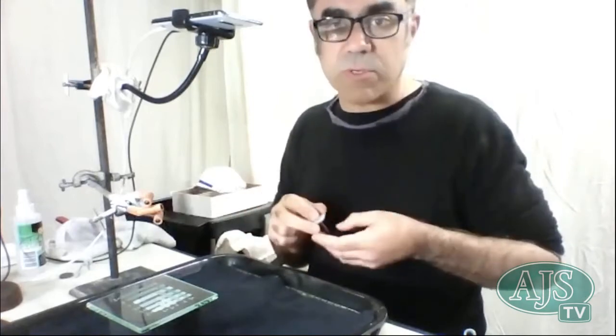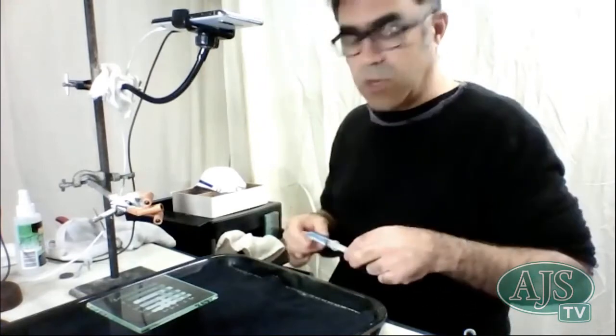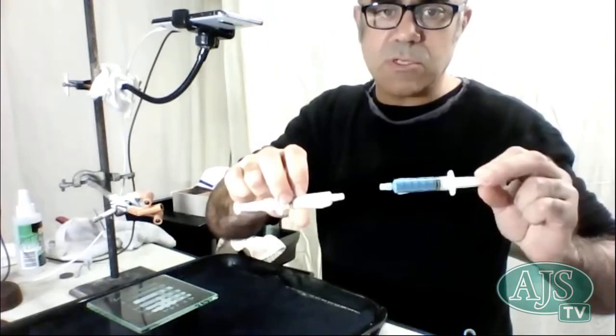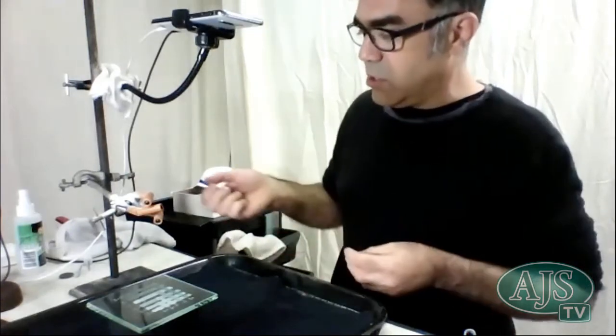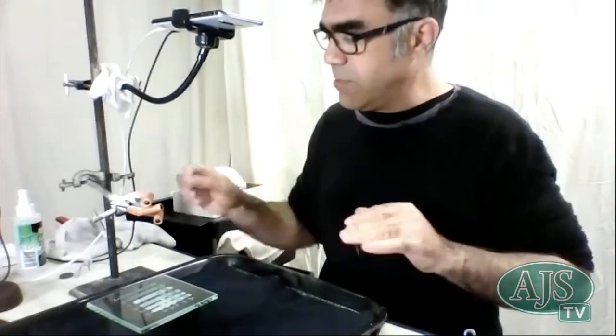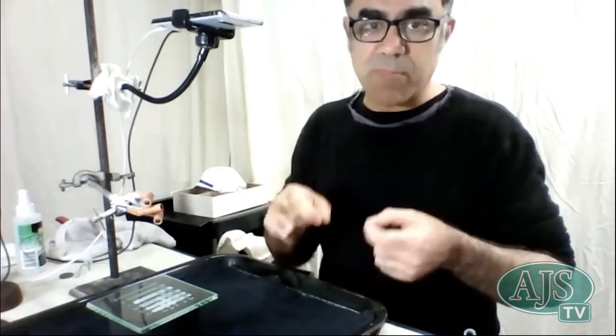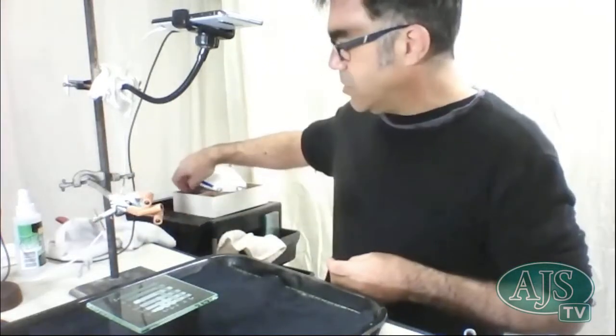Pink will take you almost to a mirror finish on the glass. And if you really want to drive it further, you can even go to investing in diamond paste, which, if you can track these down, come in little syringes, and they have, again, diamonds mounted in an oily kind of paste that you can use to take glass back to a proper mirror finish. It takes a lot of time. You can also use them for repairing any slip ups, which is fine if you're working on a big sculptural piece, but often if you're working on a small piece, it takes longer to repair a slip up than it does just to start again. But it is possible.